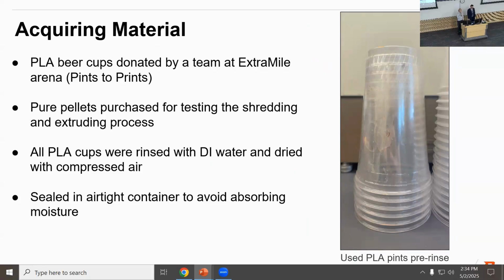So we also purchased some pure PLA pellets, Eolas brand pellets, online. We use that to test our shredding and extruding processes. All the cups that we received were washed with deionized water, no soap or anything, and dried with compressed air, and then finally stored in an airtight container so we can avoid moisture contamination.